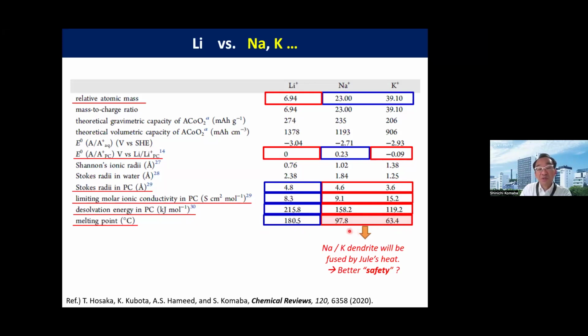Generally, metallic sodium and metallic potassium are quite reactive with water, but let us assume dendrite formation inside the battery during overcharge. Then we will have an internal short circuit between the positive and negative electrodes through the dendrite. But after heat generation, because the melting point of potassium is lower than sodium and also lithium, Joule heating will melt down the dendrite short circuit for potassium. From this consideration, we expect that sodium and potassium dendrites will be fused by Joule heat. Then we can reasonably believe there is better safety compared to lithium under overcharge conditions.